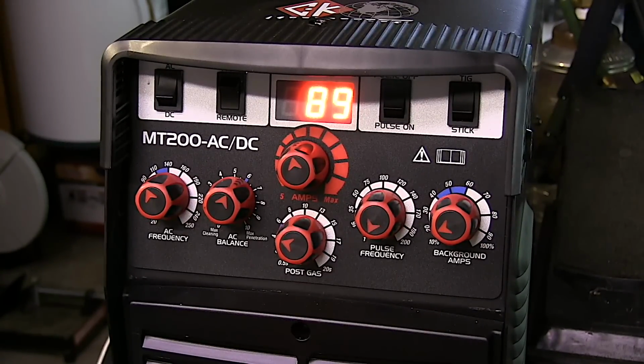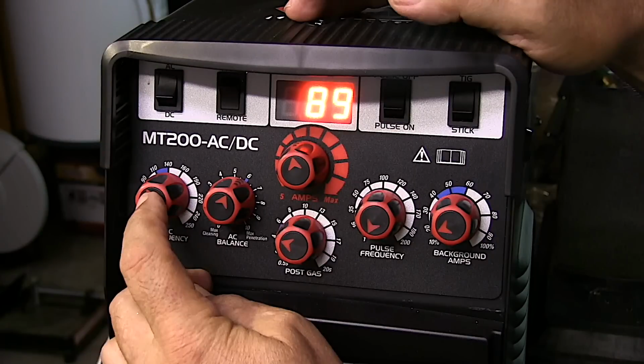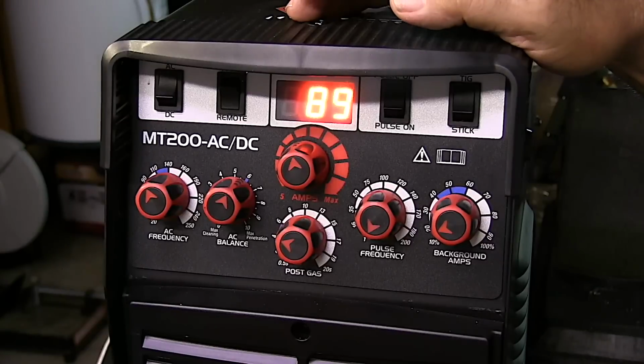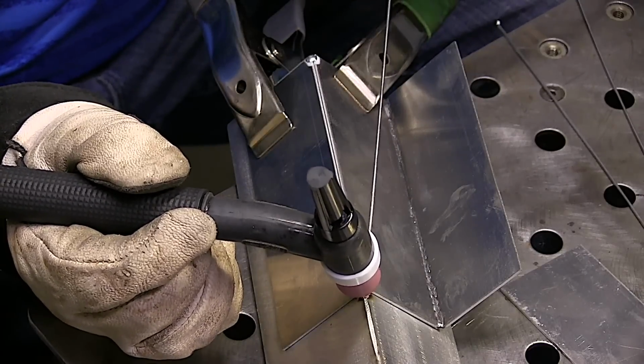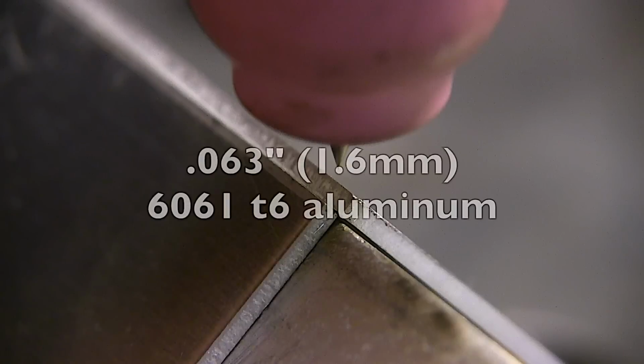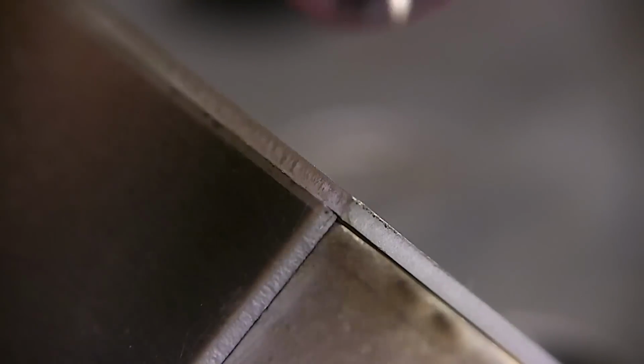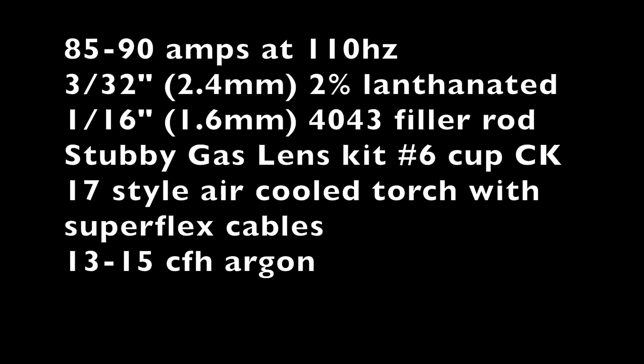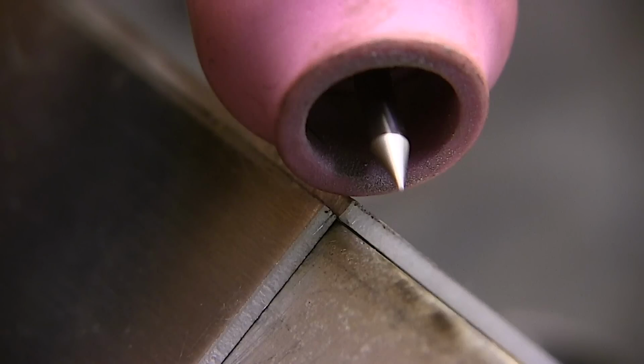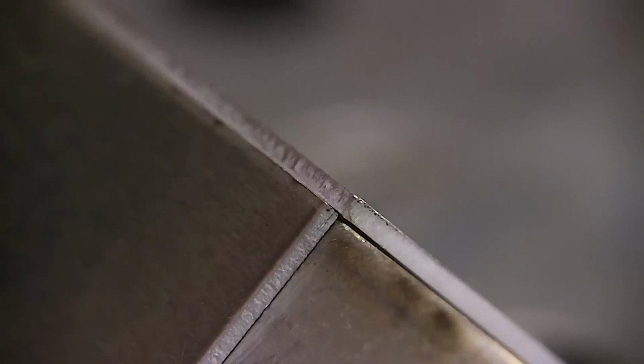The blue area on the AC frequency adjustment there is sort of a recommended sweet spot area, 110 to 140 Hertz. And so that's what I'm going to set it at for this next application. I found it's a really good setting for all around stuff, especially for something like sheet metal like this. This is 063 aluminum, not terribly thin, but thin enough to where you need a little bit of bead control. So I'm using a tapered tip and these settings.